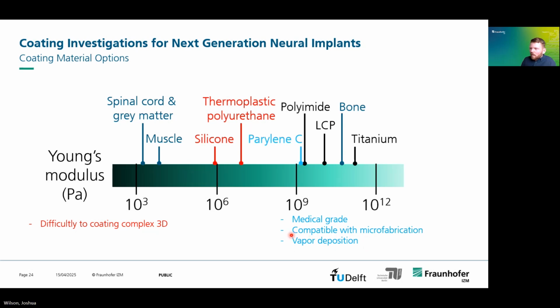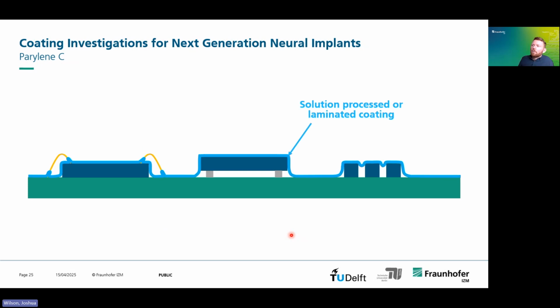So to explain the detail of this, effectively, if you were solution processing or laminating a coating on your system where you have wire bonded components, or however you were assembling your components on the surface, what you find is, this is slightly exaggerated, but you don't have perfect coverage. You have some voids. You can't get underneath structures if there are gaps. If you have very fine pitch, then you can have this tenting, and then there are more voids. And anywhere where there's voids, this is just a space for the body fluid to get in and start the corrosion process. So this is really a major point of failure.